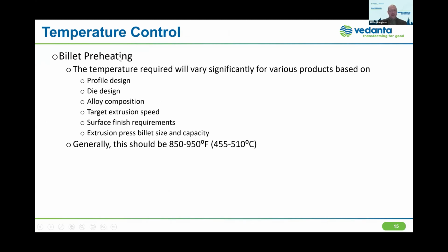Billet preheating, the temperature is going to vary depending on the product and what we're trying to accomplish. Many factors here that I will not read, but generally speaking, quite broadly, here is a temperature range that we would normally be extruding at for 6,000 alloys. And there will be exceptions to that, but that's kind of a good ballpark.